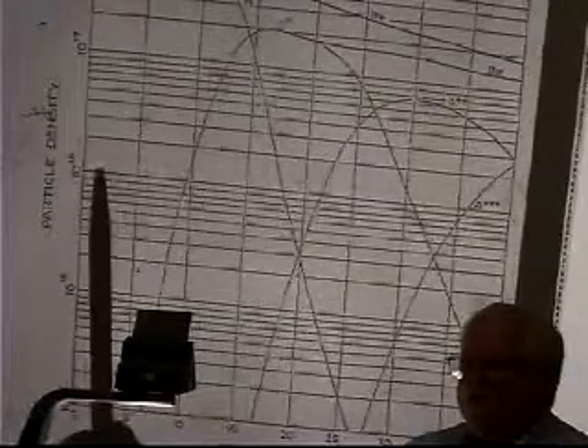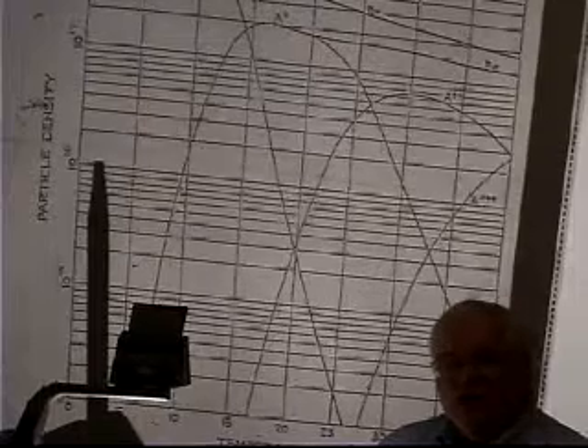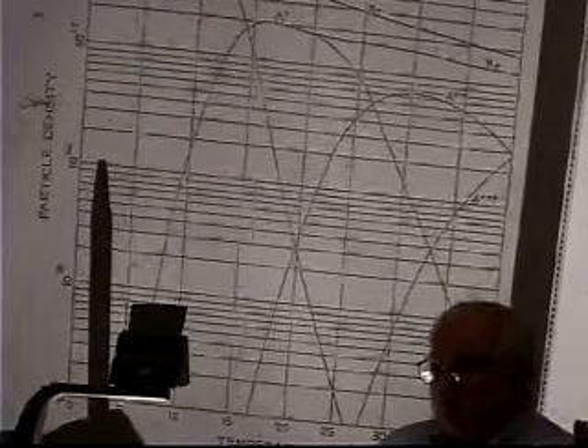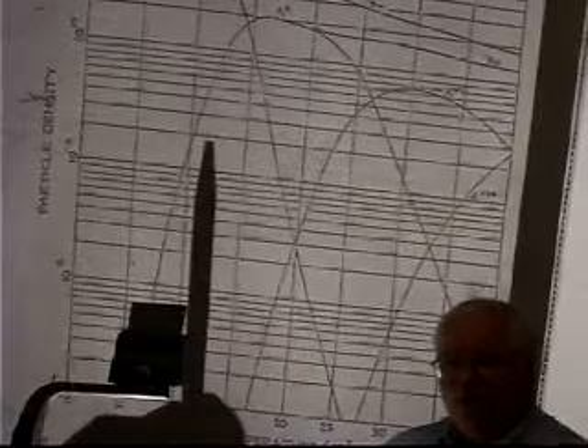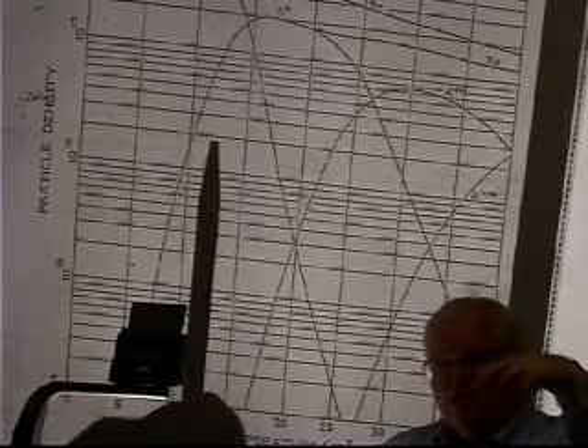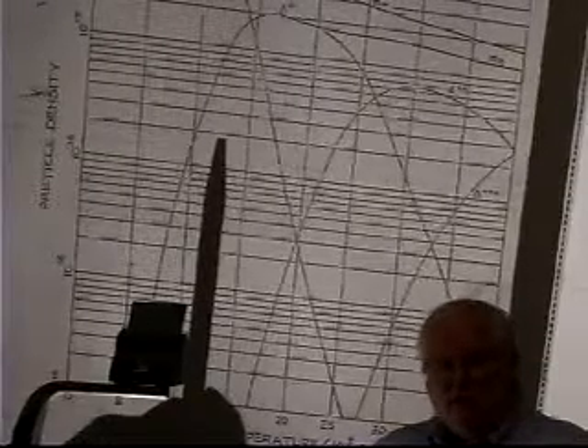It has a 5 or 6 volt ionization potential. So it drops all these temperatures down to the 5,000 or 6,000 degree range if I had a pure metal vapor arc. Now I don't have a pure metal vapor arc. I have a partially argon near the top of the electrode. In a gas tungsten arc, it's nearly pure argon. And down near the weld pool surface, it's almost all metal vapor. So I have a mixture.